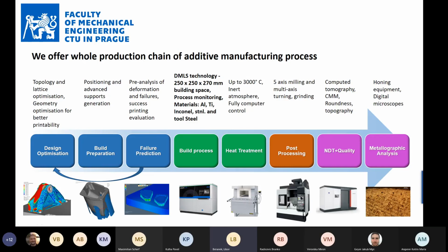Within metal 3D printing, the supports have one property that is very important. Not only do they support the structure as in the other technologies, but the powder material has a very low thermal conductivity. This is basically an isolation. So the places that are surrounded only by the powder material can be overheated quite easily. But the supports themselves have the same thermal conductivity as the aluminum part. So you can use the supports also to modify the thermal history of the part. They are not only filling the role of supports, but they also help you adjust this thermal history to fight the deformations.